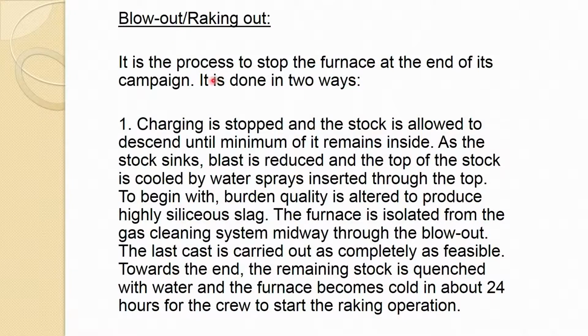So, in this process, at the end, it is done in two ways. One is charging is stopped and the stock is allowed to descend until a minimum of it remains inside. As the stock sinks, blast is reduced and the top of the stock is cooled by water spray inserted through the top. So, remember in this one water spraying is started from the top to cool the charge at the stock